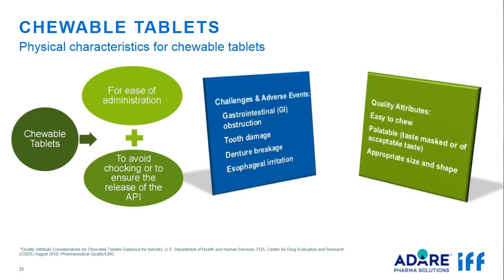Some adverse effects are reported for chewable tablets, including gastrointestinal obstruction as a result of patients swallowing whole or incompletely chewed tablets. The other reported adverse effect is tooth damage or denture breakage as a result of excessive tablet hardness, and other reports related to esophageal irritation. Due to the reported adverse events, FDA published a guidance in 2018 that describes the critical quality attributes for chewable tablets like hardness, disintegration time, and dissolution.